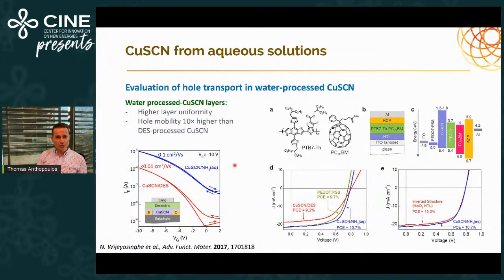We made transistors. We saw that the aqueous ammonia processed copper thiocyanate behaves better. It actually ends up with higher quality layers as compared to DES processed copper thiocyanate. We see a higher mobility from transistor measurements. And when we make the devices, we see that the aqueous ammonia processed devices were yielding higher power conversion efficiency than those based on DES processed copper thiocyanate OPVs.